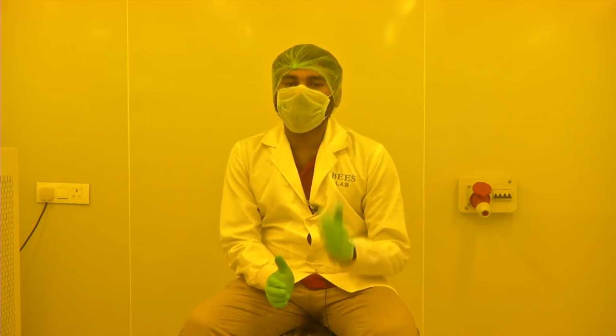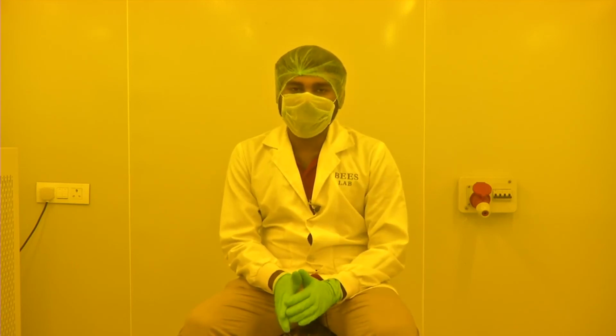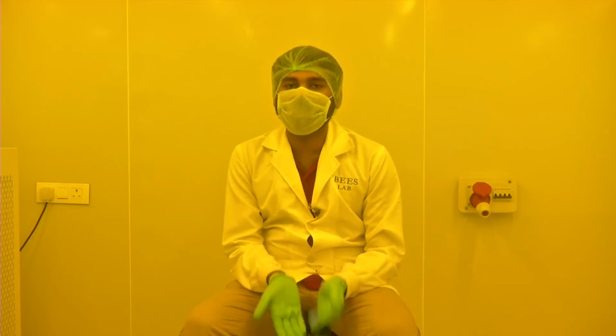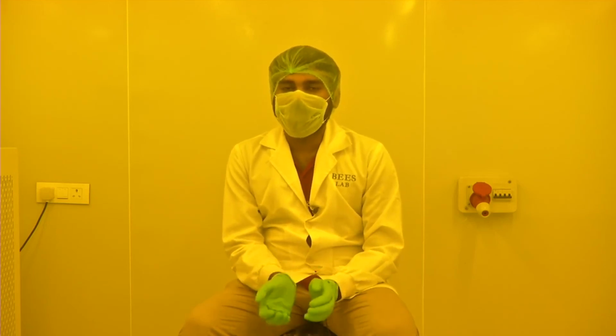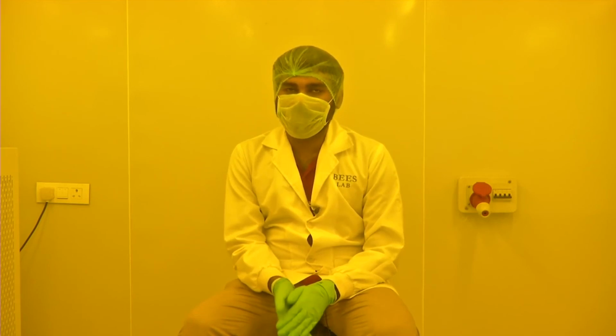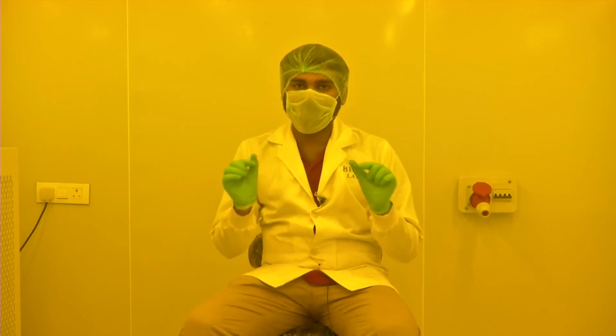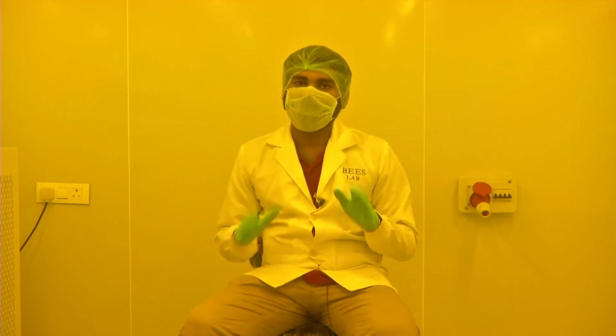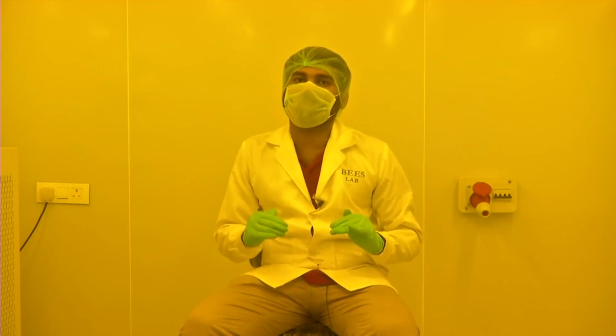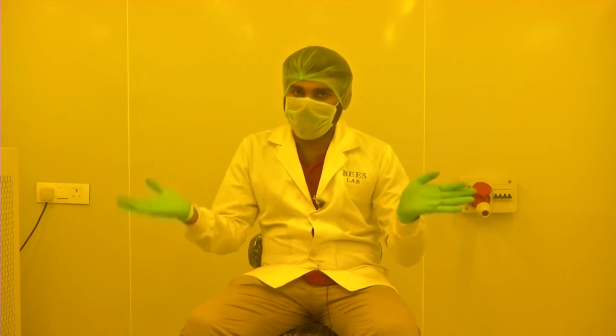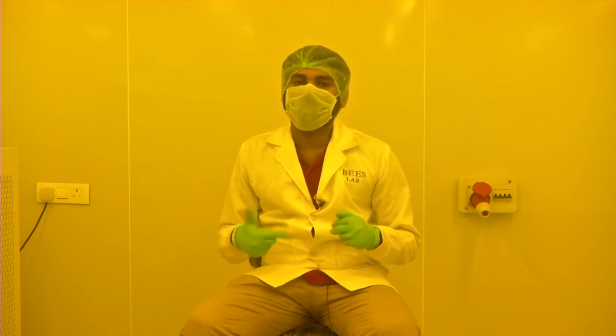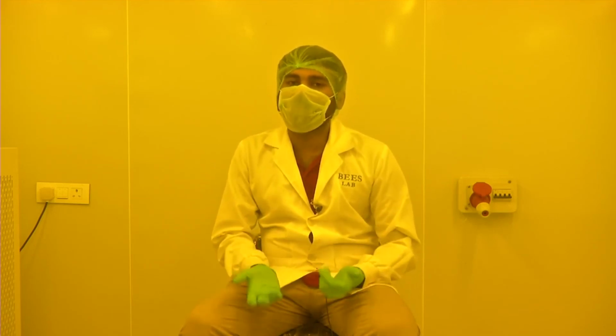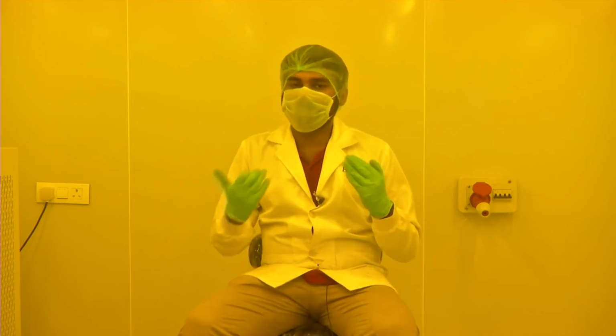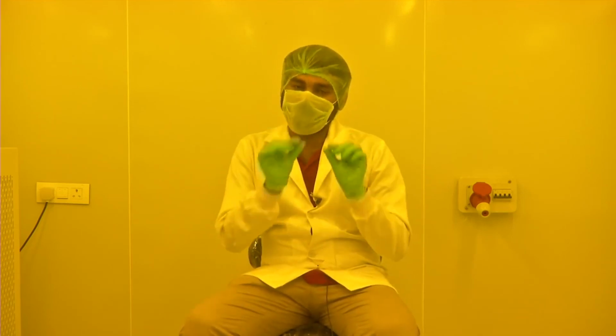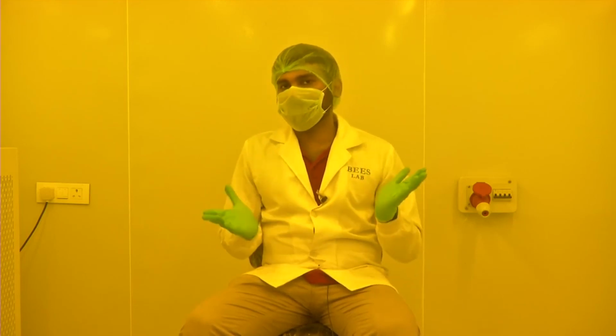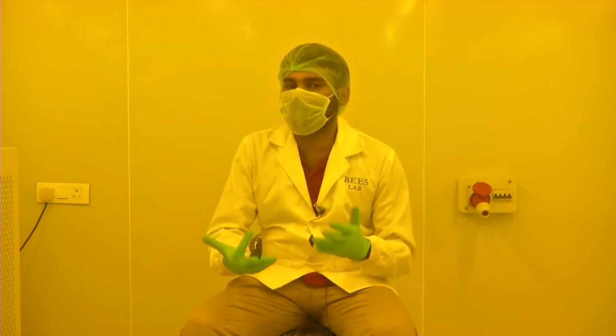Now why do we need to hard bake the photoresist? This is because let's say there is a subsequent process. I have gold deposited, and after the photoresist exposure I will use gold etchant. Wherever the photoresist hardens and remains, the gold below it will get protected. Everywhere else the gold and chrome gets removed. Once that process is over, you can remove your photoresist through an acetone IPA dip. The photoresist will go, and only below where the photoresist was, the gold and chrome will remain. That is the last process of microfabrication, which is a subtractive process.